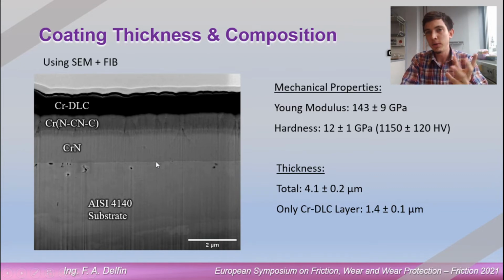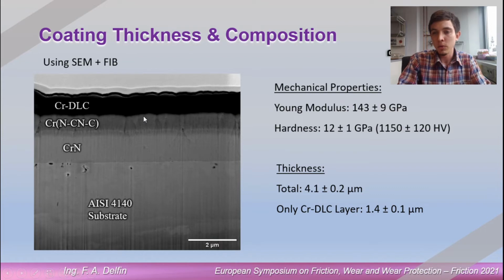It depends on the spins of the carousel inside the PVD coating and the position of the sample inside, but it's pretty much 4 or 5 micrometers. And the DLC part of the coating, the top layer, is 1.4 or 1.5 micrometers thick. The mechanical properties, with a Young's modulus around 140 gigapascal, as we can expect, and the hardness around 12 gigapascal or 1200 HV roughly.